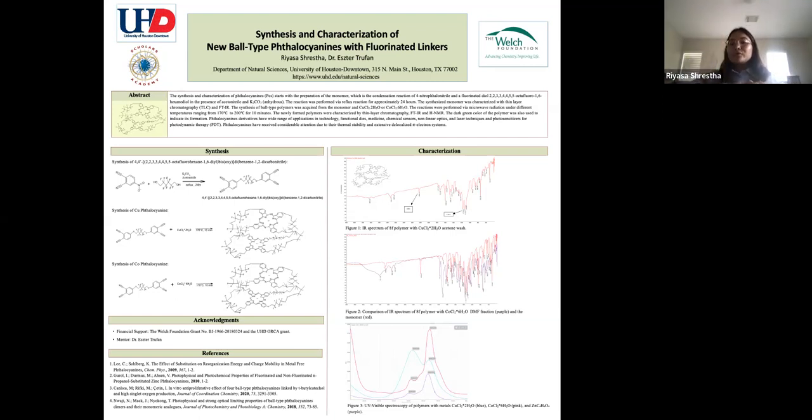After the TLC is done, when we look at the plate under the UV, you will see some colorless stuff moving up. That is the stuff that we don't need because my compound is dark green, and I will extract only the dark green line that's left. The colorless stuff can be the monomers or other stuff that is not the ball type phthalocyanine that I need. So it's a repetitive process of purifying it. I will continue to extract just the dark green compound, check with the IR, and then do the TLC again. Okay, great.